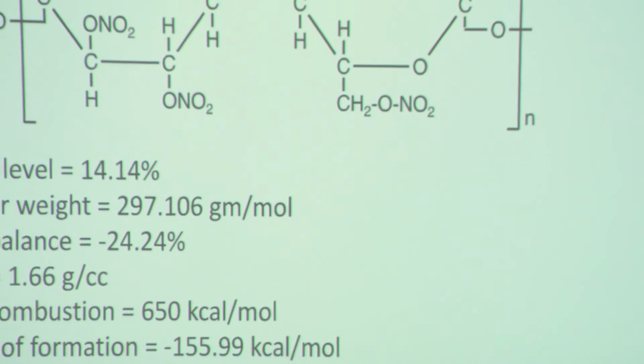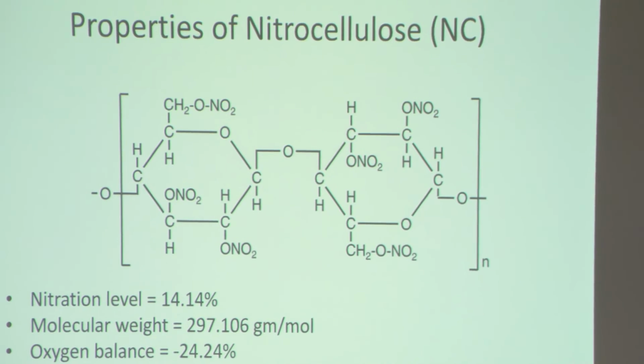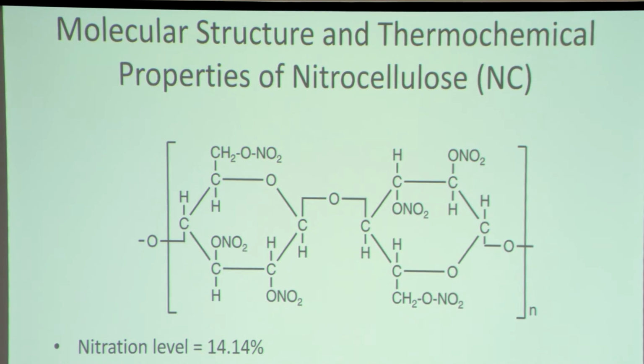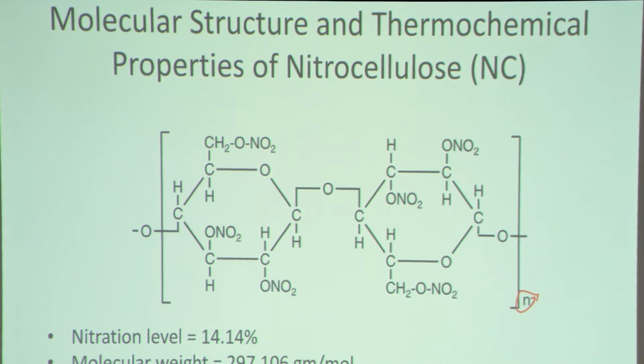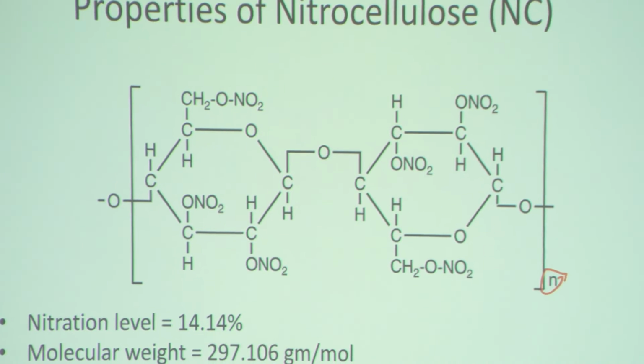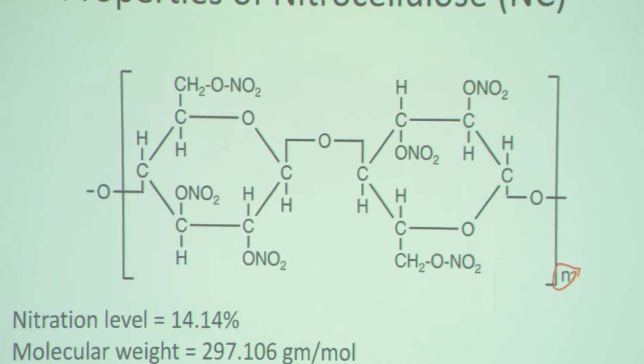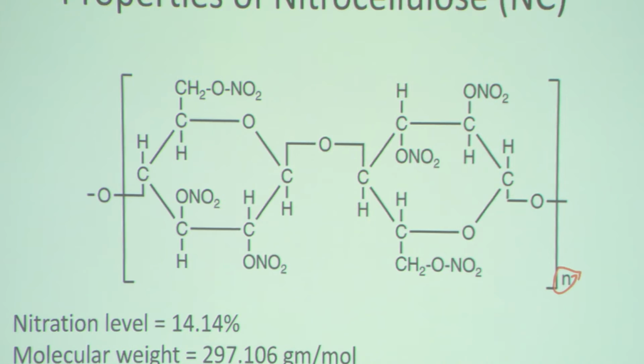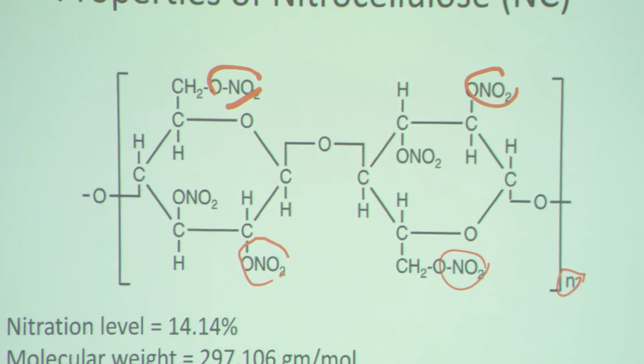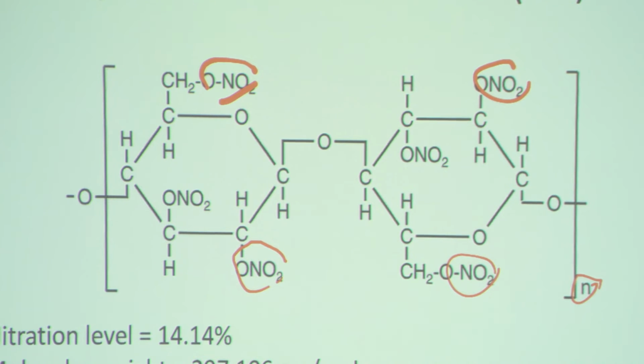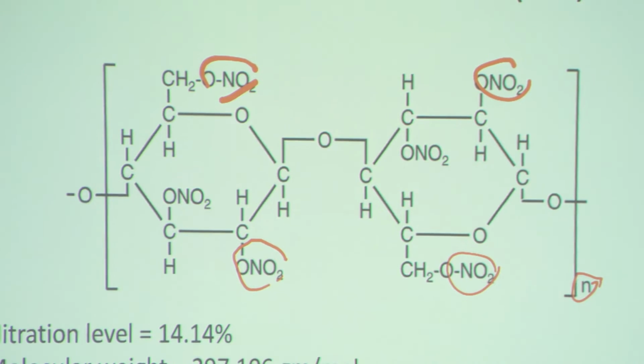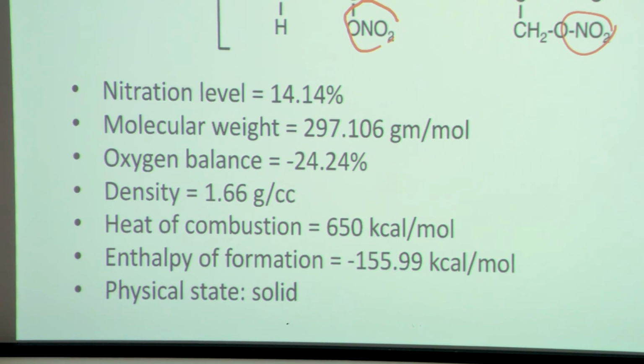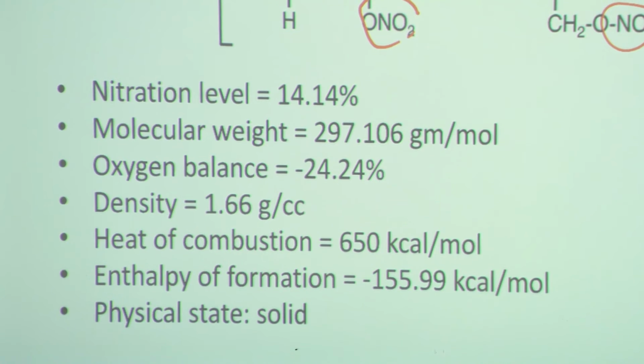Okay, so here's an example of the molecular structure of nitrocellulose. And you can see it's a repeating structure. The n here basically means that this structure repeats itself. So you can see it consists of a ring structure of carbon, mainly with some oxygen in the ring. And then off of the ring structure, cellulose has been nitrated. So basically these NO2 groups, nitrates, have been added to the rings. And that becomes the oxidizer for the carbon and hydrogen that's in the ring structure. Okay, so this is an example of a nitration level of 14%, molecular weight of 297, oxygen balance of minus 24%. So again, it doesn't have enough oxygen to fully oxidize the carbon and hydrogen.